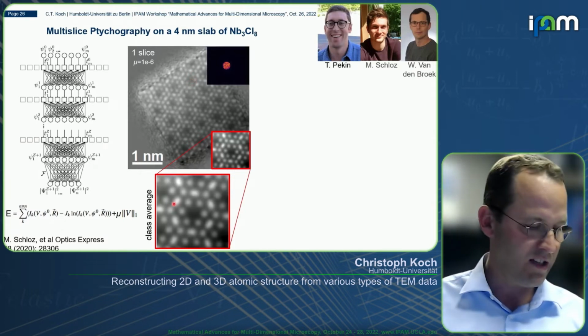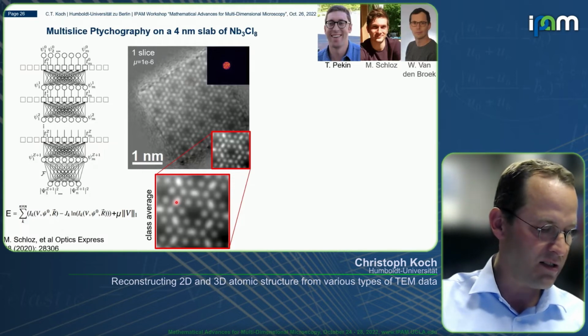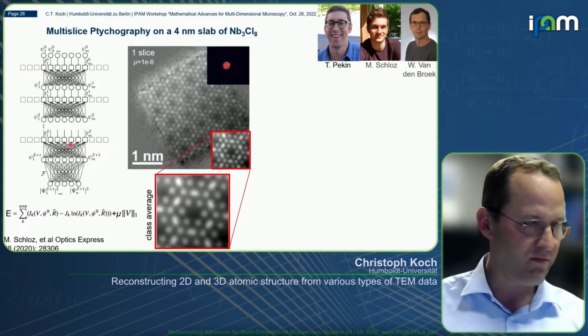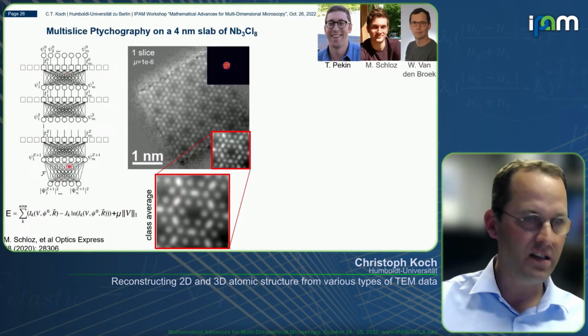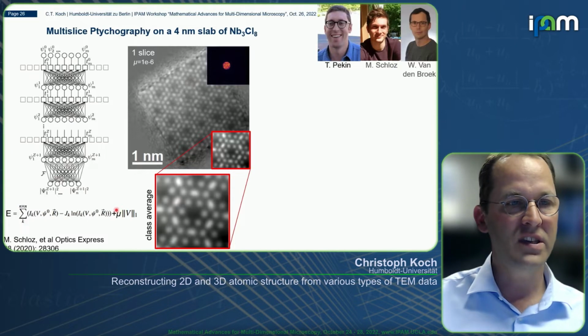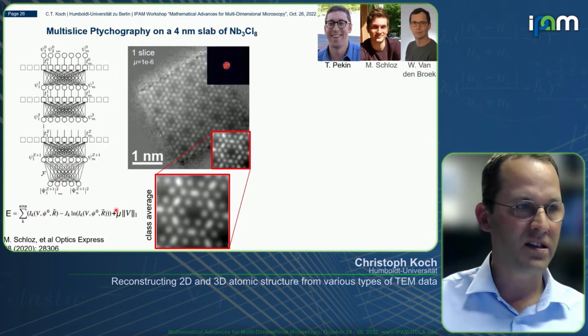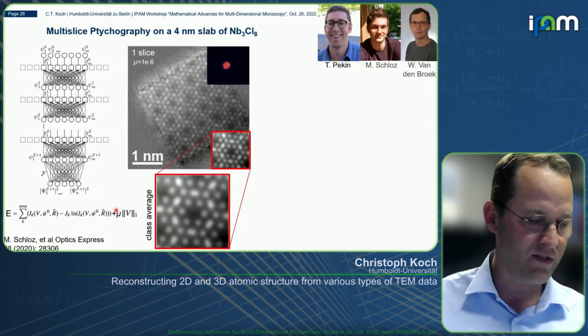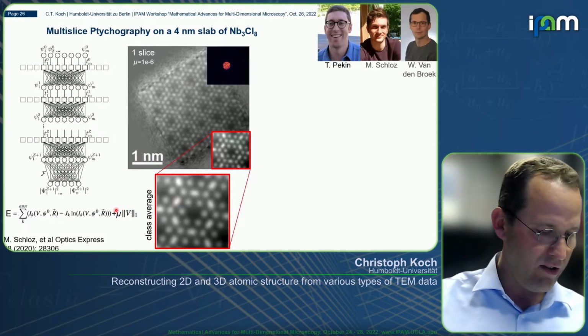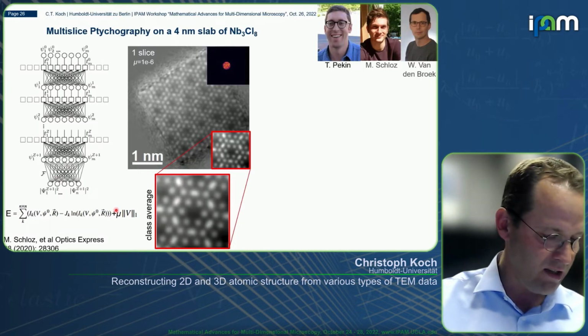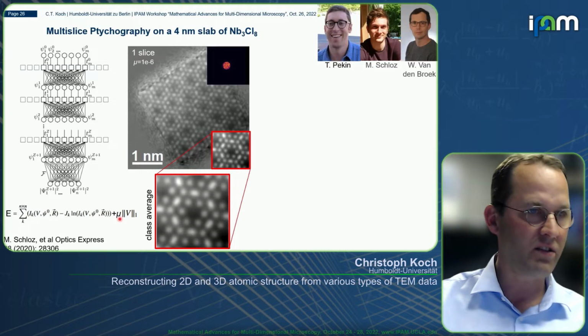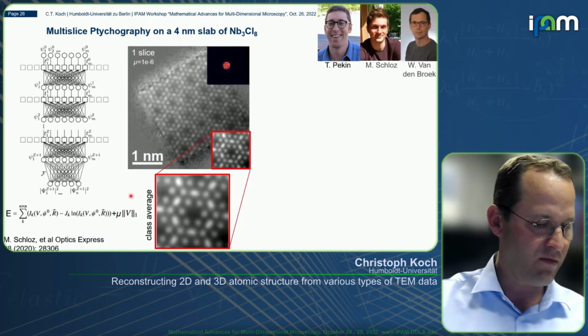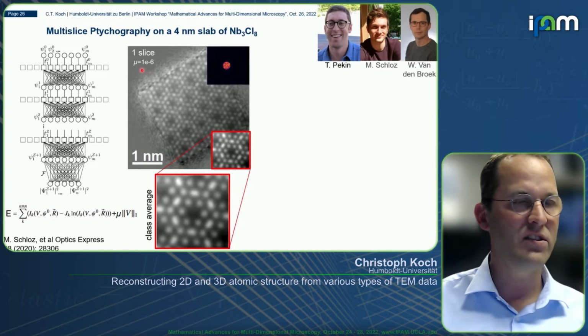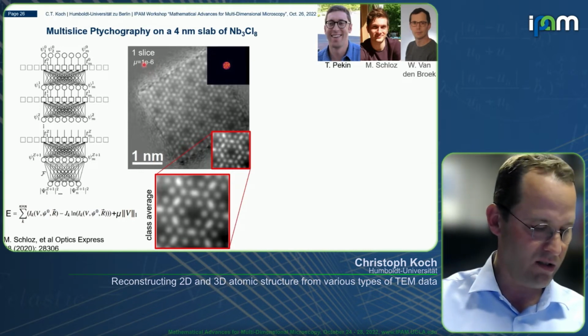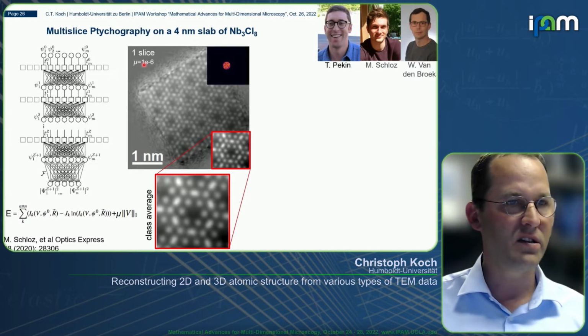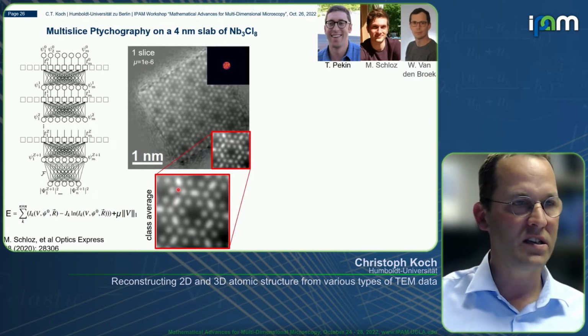these atoms here. So what we did is we ran it through this multi-slice reconstruction algorithm, also applying constraints. In addition, we tested if the data could be reduced. Do you really need all these gigabytes of data in order to do the reconstruction? If we just apply a single slice and set this mu parameter, which is a weight on the L1 regularization of the potential, to very small numbers, say 10 to the minus 6, we basically have a non-regularized reconstruction, and we don't see this dumbbell resolved. Even if we apply some regularization, it wouldn't be resolved.